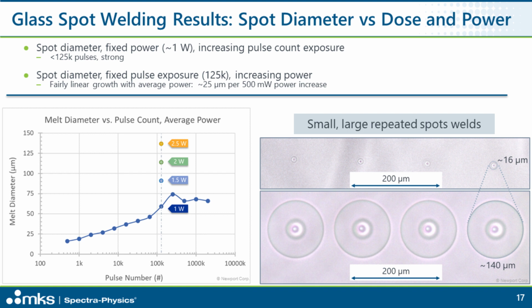So in some cases, spot welding might be a preferred approach for joining, bonding a couple of glass plates. So we did a series of experiments using a variable power and a variable number of pulses. First, let's talk about the variable number of pulses. The data plot on the left shows a very low pulse count, below 1,000, maybe a few hundred pulses. And we increase, this is a logarithmic scale, so we increase quite strongly up to over 100,000 pulses, stationary pulses at 1 watt. We see the growth in the melt diameter, which is the vertical axis. And then as we go beyond 100 or 125,000 pulses, we see some instability in the melt region.